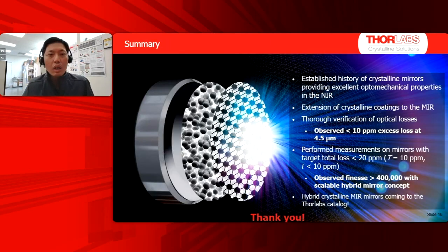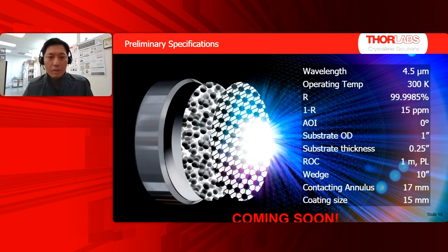All right, and so I'm excited for these results, and even more excited that these mirrors will be coming to the catalog. You can see the preliminary specifications here. They'll be at center wavelength of 4.5 microns at room temperature with a reflectivity of about 1 minus R, about 15 ppm. Typically, they will be higher reflectivity than spec, but we've been a little conservative here. They'll come out on 1-inch substrates as shown. You can get them with 1 meter radius curvature or planar.